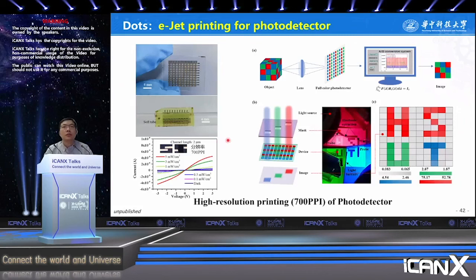In addition to the display, it can also be utilized to fabricate a full color photo detector. The image is shown as the left top figure. Each pixel contains 3 sub-pixels: red, blue, and green. The feature size is 2 micrometers, and the resolution reaches about 700 ppi. The photo detector becomes flexible when it is stripped from the glass substrate via laser lift-off.